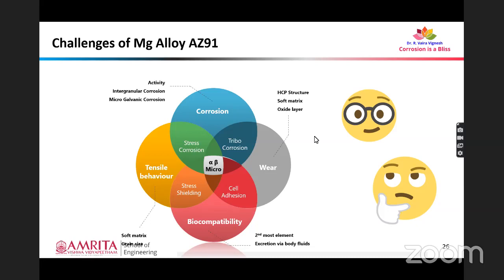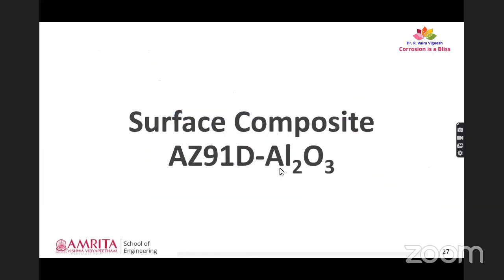And coming towards cell adhesion and characteristics such as tribocorrosion, magnesium alloy, since its density is very low, it lacks in terms of wear. So it has a high wear rate. So if we are able to make a composite or do a process to enable wear resistance, then it could be considered as an effective implant material too. So we'll just go towards the surface composite that is manufactured using nano phase aluminum oxide.